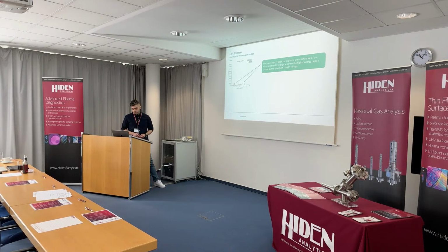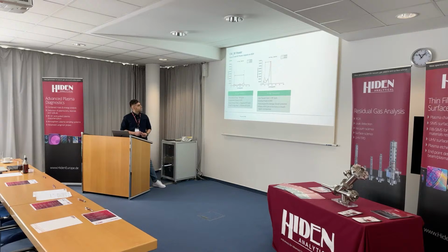So the lower energy peak corresponds to the influence of the minimum sheath voltage, whereas the higher energy peak is caused by the maximum sheath voltage. And why do we see these differences in the width of the peaks? At lower frequency, the ion transit time is almost equal to the RF cycle, so we see more separated peaks. And at higher frequency, the ion transit time is much higher than the RF cycle, so the peaks are more unified, and ions respond to the average sheath potential.